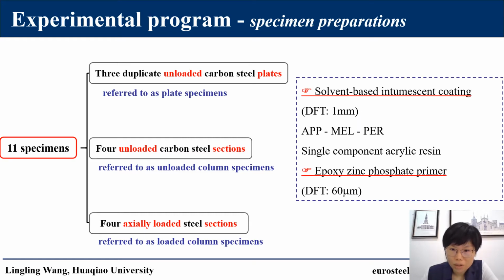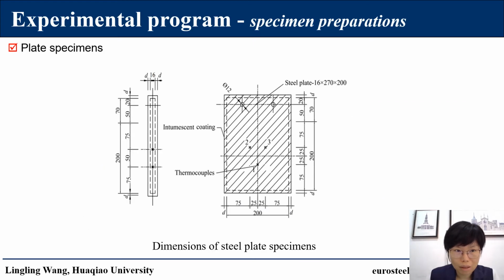An epoxy zinc phosphate primer was used on the surface of specimens before applying a solvent-based intumescent coating. The steel plates were protected by a primer and an intumescent coating on all sides. 3 thermocouples were embedded in each steel plate at the mid-thickness.